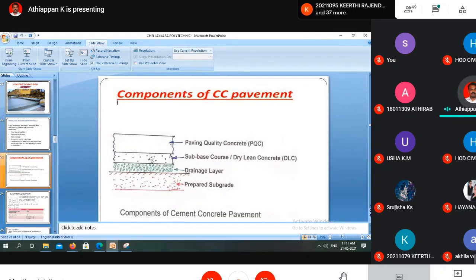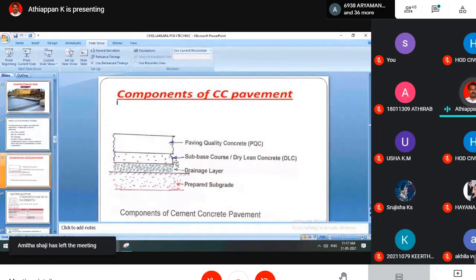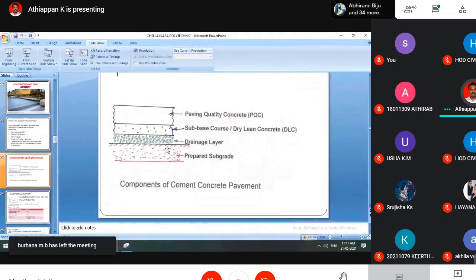So you may ask why we don't provide any joints in the subbase layer. We need not provide joints in the dry lean concrete. The reason is that it is a 1:4:8 concrete. You will have very high voids, so those voids will accommodate the expansion and contraction. So you have to make this pavement quality concrete an independent layer. Okay. So